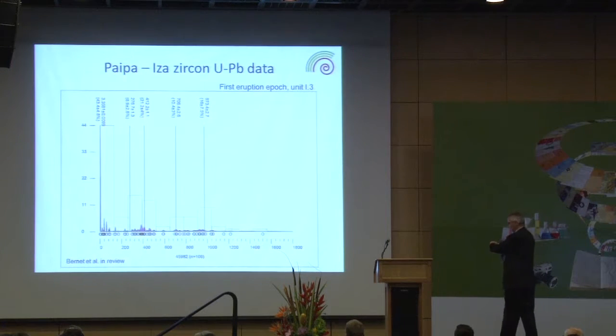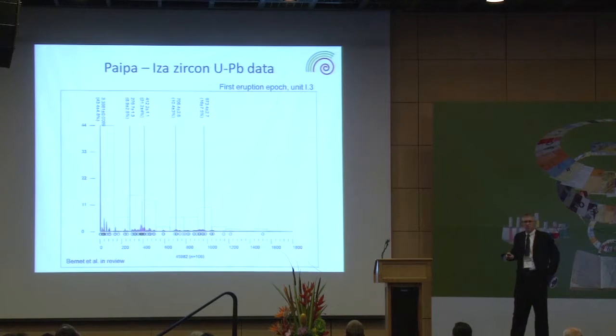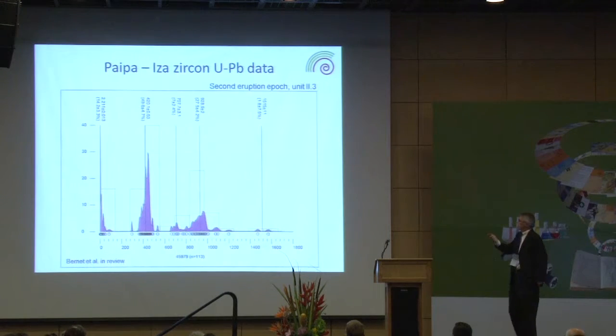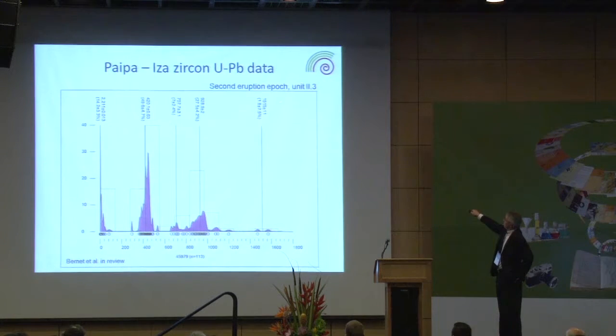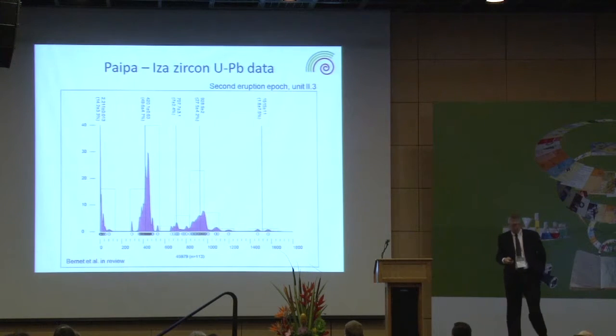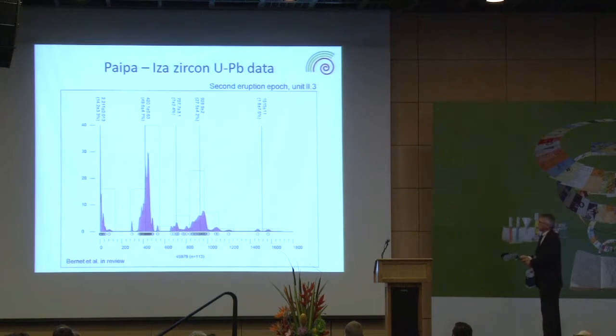So if you look at the uranium-lead data, we can also get a whole spread, the same thing. We have ages of about 3.3 million years here in this sample from the first eruption episode, and then older peaks, not all the way spread out, basically the same range that we saw in the Eastern Cordillera before in the river analyses. And then from the second eruption episode, we get a first peak at about 2 million years, and then we have these older peaks as well. So also in there we have this recycling signal.